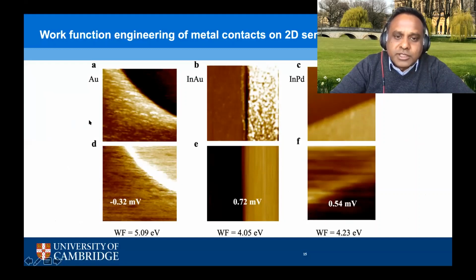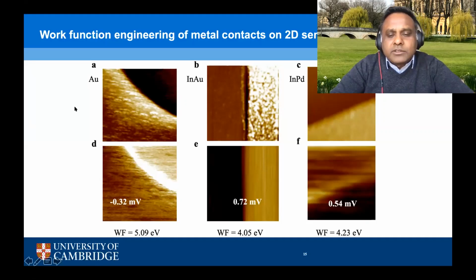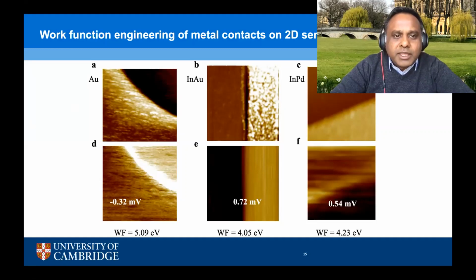Measurements have also shown that these contacts are actually quite stable all the way down to low temperatures of sub-4 Kelvin as well. So we felt very comfortable over the last year and a half that we're able to make good N-type contacts using indium as the electrode. But to move towards this tunnel FET idea that I alluded to earlier, we also require P-type contacts.